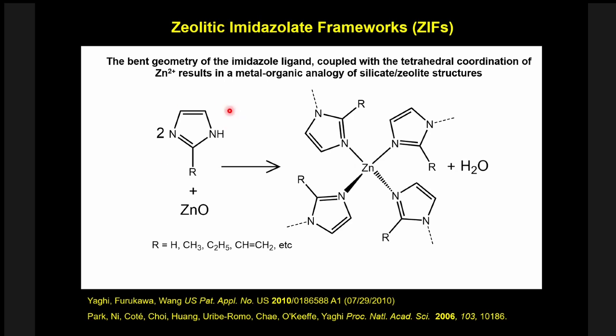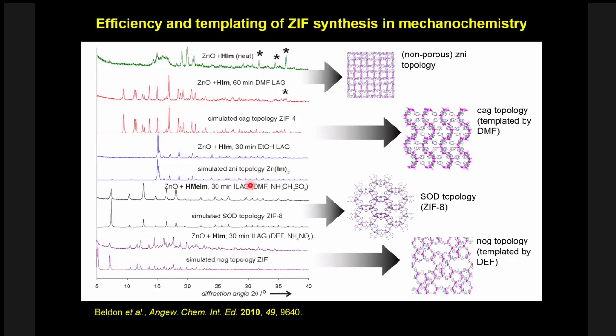You take this imidazole ligand, they tend to be cheap, readily accessible. You take some metal oxide, zinc oxide, trivial, you grind it together. Maybe you catalyze it a little bit with some protic salts, or maybe you add a trace of liquid to both kind of lubricate the reaction or to actually help organize the structure into a certain framework type. And it works beautifully. So here are some examples here. Don't worry about these powder diffraction patterns. Just check out the structures we can make.